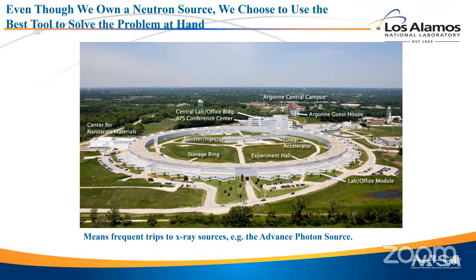We use facilities like the Advanced Photon Source just outside of Chicago, or CHESS up at Cornell, not too far from here, where they produce X-rays in a synchrotron. Again, this is about a mile in circumference. The beamline that we use produces X-rays up to 100 kiloelectron volts. At that energy level, I can start to penetrate macroscopic amounts of metal. I can penetrate 2 centimeters of titanium, for instance, with a 100 kilovolt X-ray beam. I can penetrate 0.5 millimeter of uranium, which gets us into the area of interest for Los Alamos.